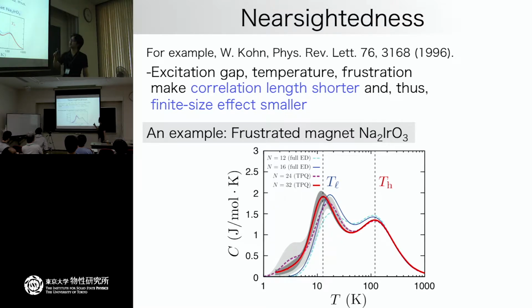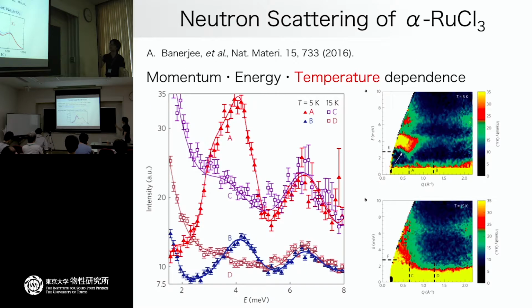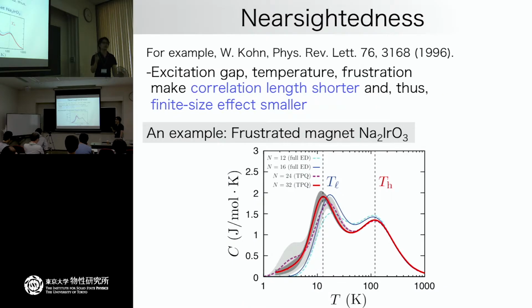For example, let me remind you of the heat capacity data from the Na2IrO3 Heisenberg Hamiltonian. Above more or less 30 Kelvin, which is 1/10 of the dominant coupling, the size effect is nothing. Even if you go below, still the finite size effect is quite small. So in this sense, for frustrated magnets, the finite size effect at finite temperature becomes really small. Not so small, maybe you want to say, but anyway, we can control the finite size effect at finite temperature.